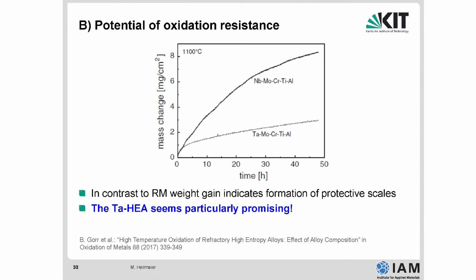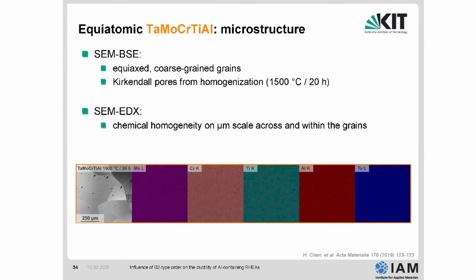But we want to develop high-temperature alloys. So what about oxidation resistance? Here I've shown you again the mass change at 1100 C for these two alloys. The niobium alloy is not so promising, but the tantalum alloy, tantalum, molybdenum, chromium, titanium, aluminum, shows very low mass changes at 1100 C. So this should be of interest for further development. First of all, you have to make the alloy, equiaxed coarse-grained. You should check again chemical composition, chemical homogeneity.